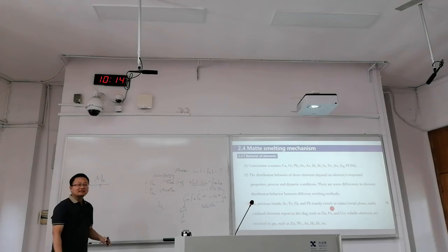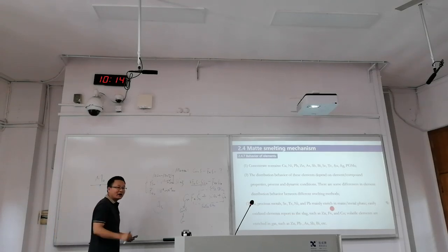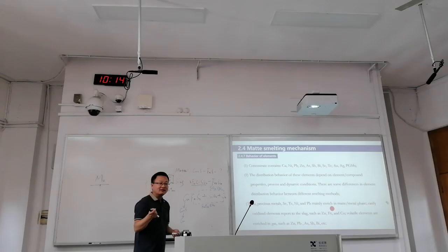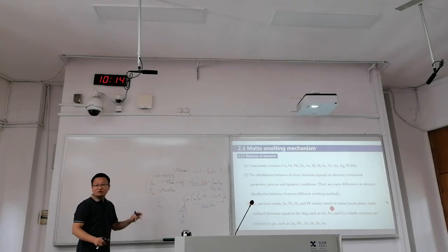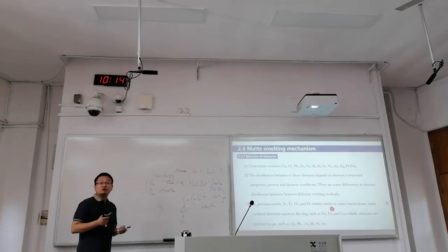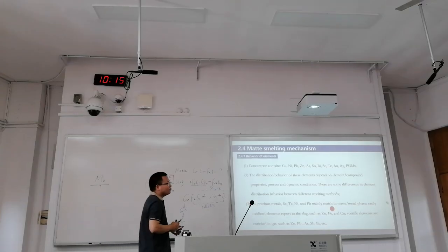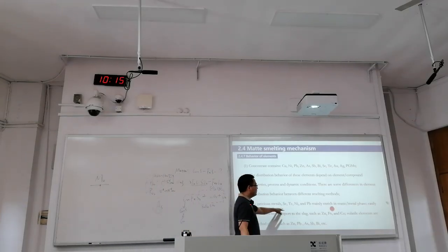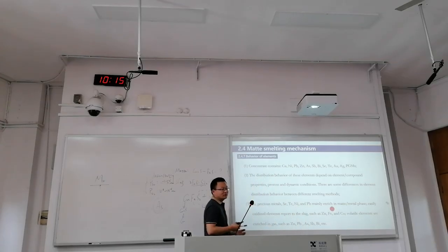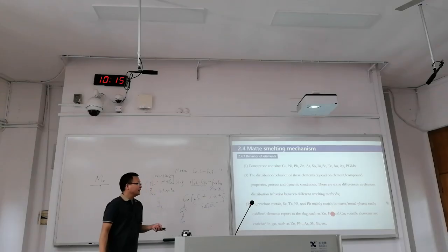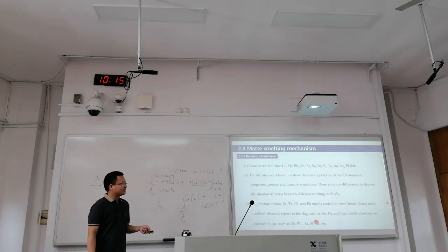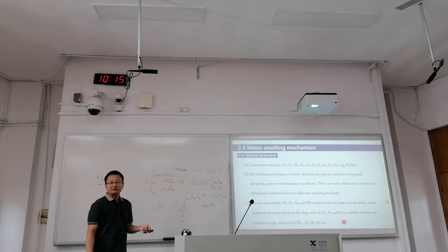But from 2020, there are two big mines in China, one from Australia, and one from Argentina. So we have copper mines which are rich in this. So you will have an idea where Mo, or molybdenum, will report to, and we are analyzing that. We are recovering it. Here we know precious metals, lead, nickel, and selenium, tellurium will be in the metal phase, and some other elements like zinc, iron, cobalt will be in the slag.